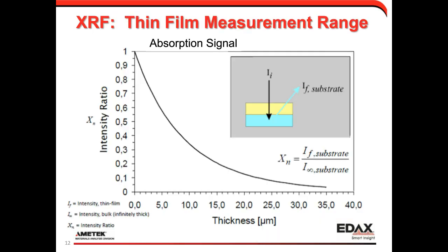Okay, another form of making measurements: instead of measuring directly the emission signal from the coating, we can measure the substrate signal and look at its intensity as a function of the coating on top of it. So now that substrate signal is going to be absorbed by the top layer. So this plot looks a little bit different. On the x-axis, we have the thickness range. On the y-axis, we have the signal intensity ratio again.